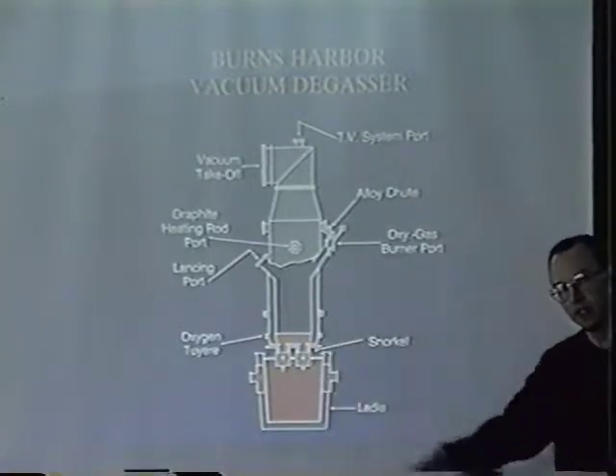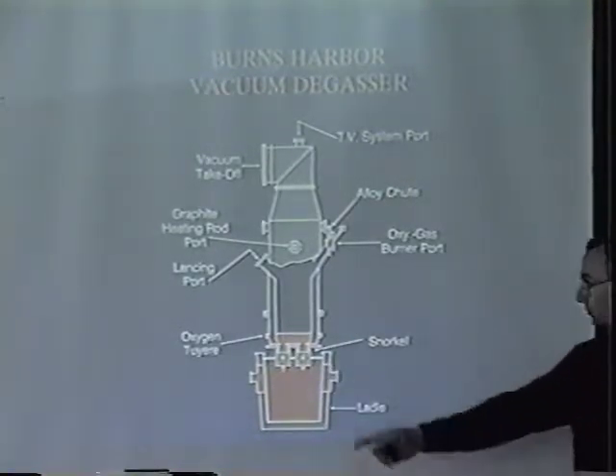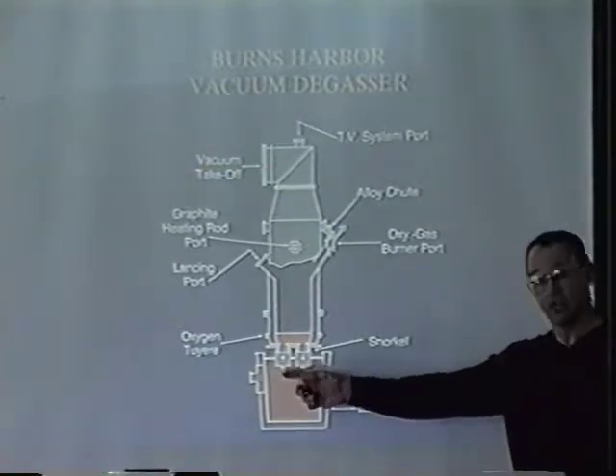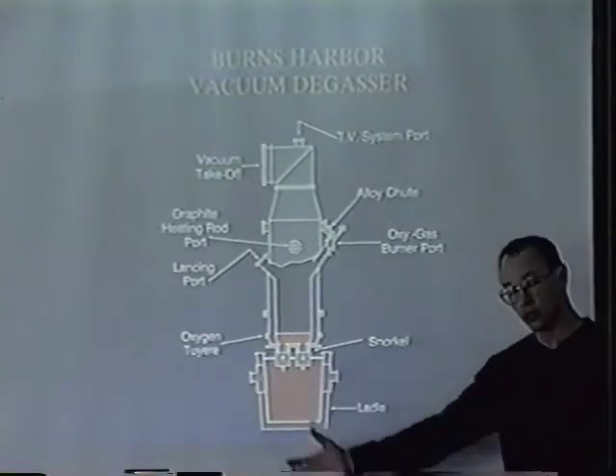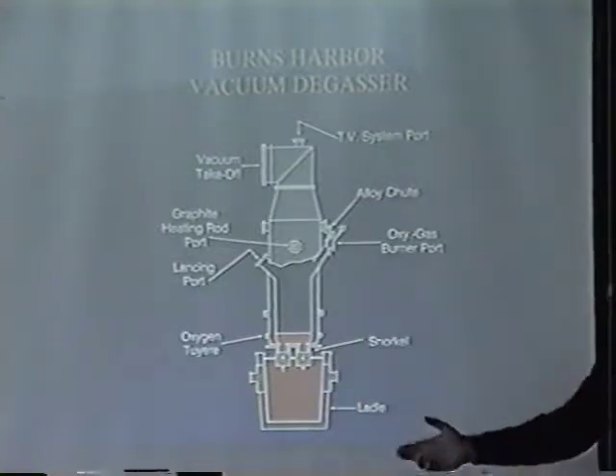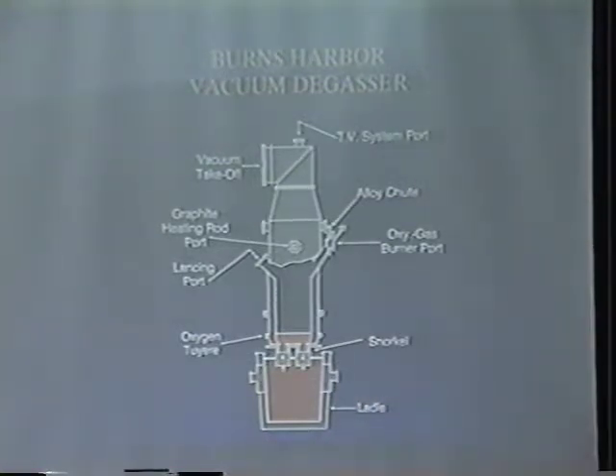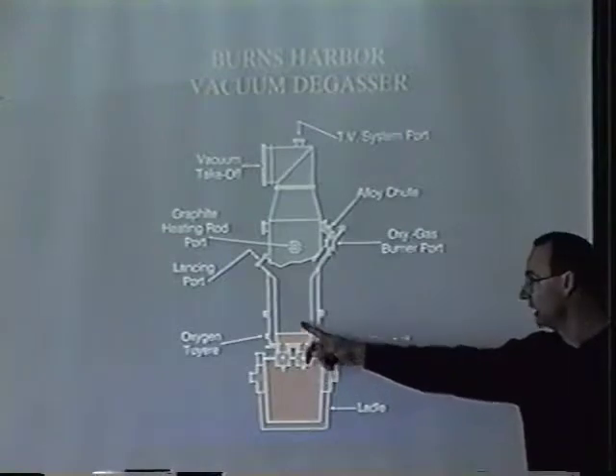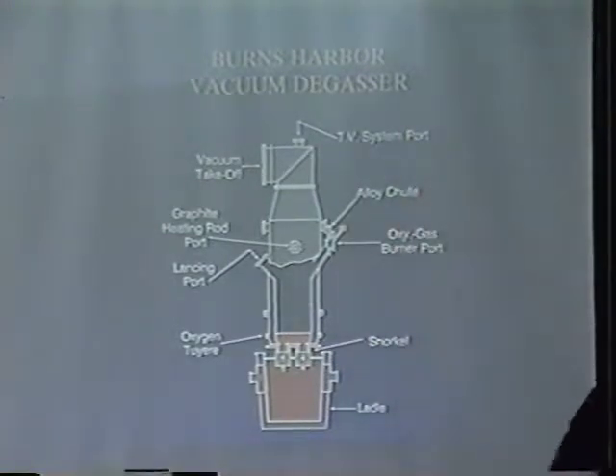And it takes a tremendous amount of force, because you have to imagine, steel's heavy, and you're lifting it with a vacuum up into the chamber. Not only are you lifting the steel, but the carbon is combining with the leftover oxygen in that steel and forming CO and CO2 gas, and the degasser's sucking it out. So with the degasser, we suck the excess carbon and the excess oxygen out of the steel, and we're left with a really low carbon steel. And that's how we remove carbon.